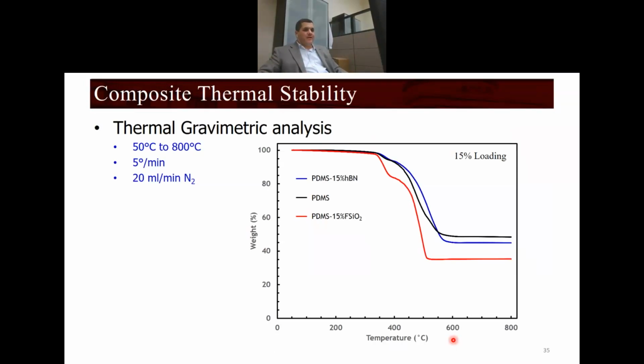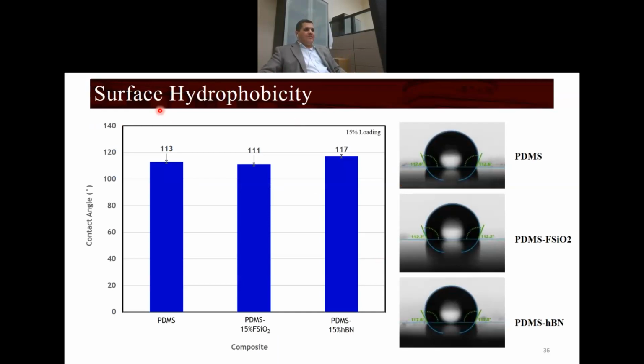This is a TGA also. This is a very typical curve for the commercial ones as well. The remaining weight percent is very much similar to what we typically get from the commercial. If you run any commercial coating, you get very much the same curve. This is the hydrophobicity before any aging or before any testing, very much within the expected hydrophobic range.